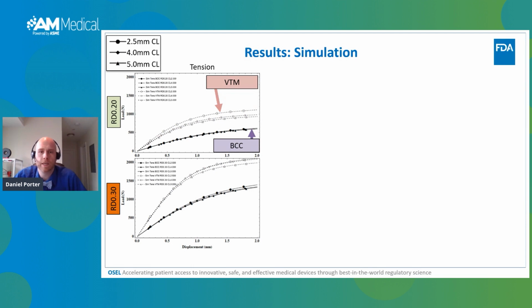So quick setup for this. In the legend up in the top left, circles are the smallest strut diameters, diamonds are the middle range strut diameters, and triangles are the largest strut diameters. Y on these graphs is the load, X is the displacement, and the majority of these plots go out to about 2 millimeters of displacement. Dashed lines are the Voronoi or stochastic lattices, and the solid black lines are the BCC or body-centered cubic lattices. What you'll notice for tension, which is what we're showing here, is that the simulation results show that they give relatively the same performance. The Voronoi is technically different in design every time you generate a new design, so that may explain why we get a little bit of difference here in the